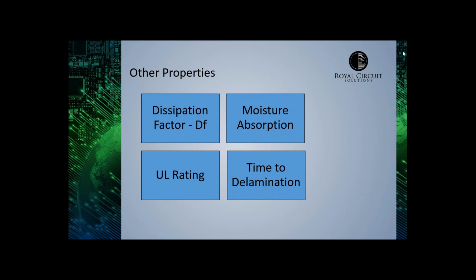Time to delamination. There's a time to delamination at different temperatures. Usually there's two numbers for this. 260 and 288 are the most commonly used. All that is showing is the time until the material starts to delam, come apart, at that given temperature. Obviously, if you're submitting a board to some very high temperatures and you see a very low time to delamination, you might want to reconsider the material usage for that part.